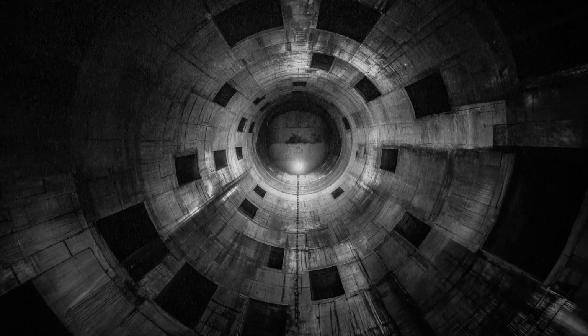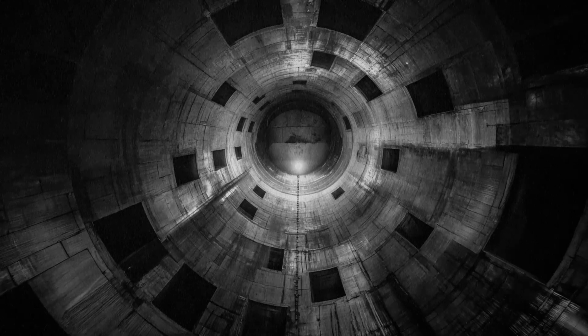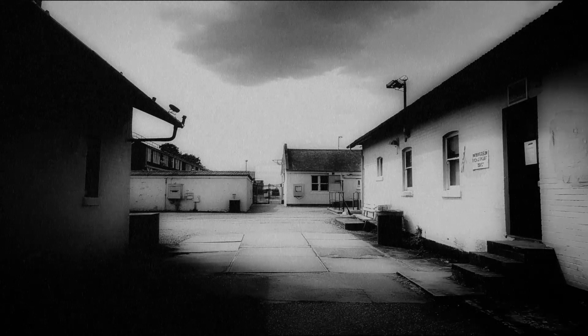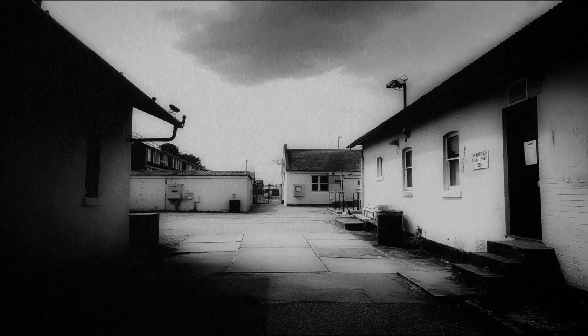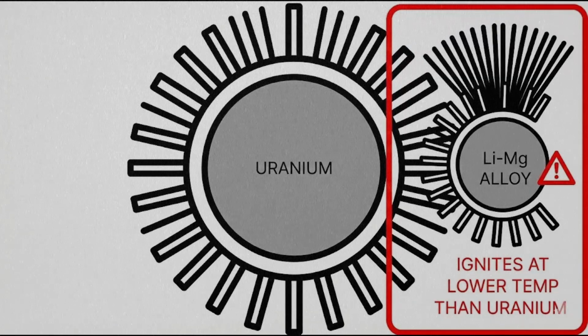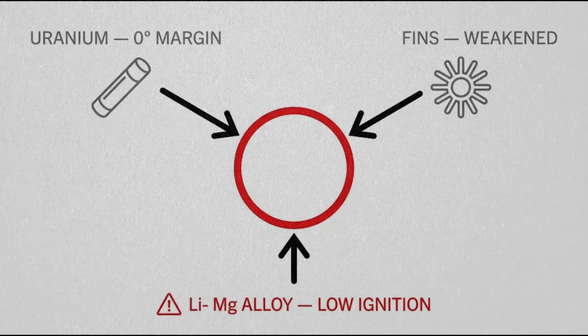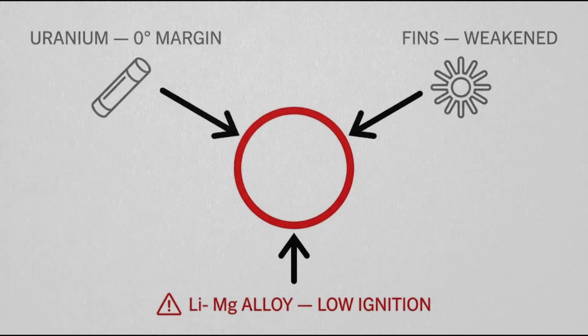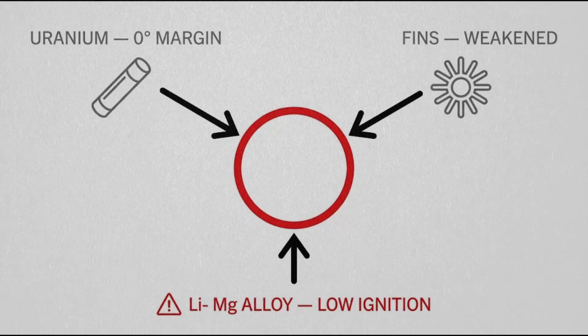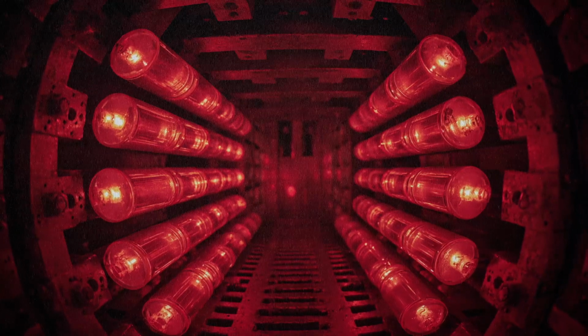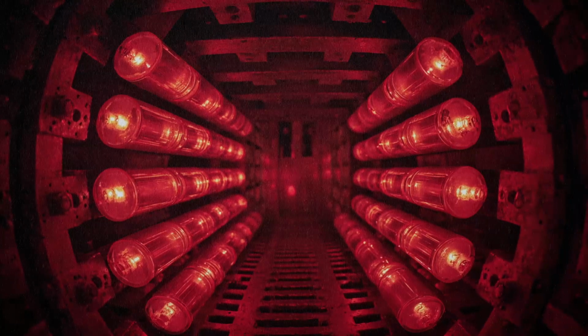And there was one more element in the core that was never part of the original design. Britain's hydrogen bomb program required tritium. To produce it, lithium-magnesium alloy cartridges had been loaded into the reactor, a material that ignites at temperatures lower than uranium. Natural uranium with a 0-degree safety margin. Cooling fins deliberately weakened. A foreign alloy that burns at lower temperatures than the fuel itself. The reactor was not just carrying fuel, it was carrying an accelerant.